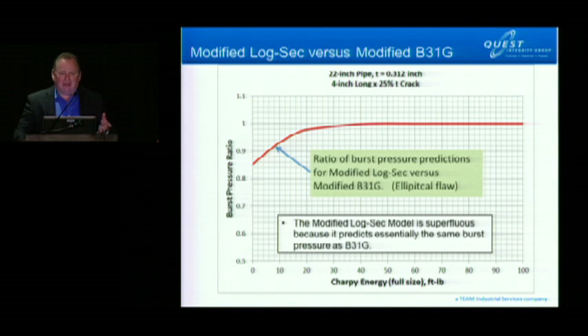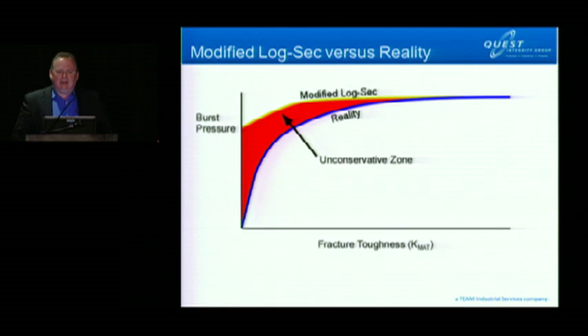In fact, that makes it superfluous because it gives you almost the same answer as B31G, so why do we need two equations to predict plastic collapse, which is all this is doing. It's not predicting correctly in either the linear elastic or the elastic plastic regimes. So if you look at what this means in reality, it produces unconservative results. The blue curve is my representation of reality, of what we expect burst pressure versus toughness to look like. The yellow curve is modified log secant, and that red area represents unconservative predictions.